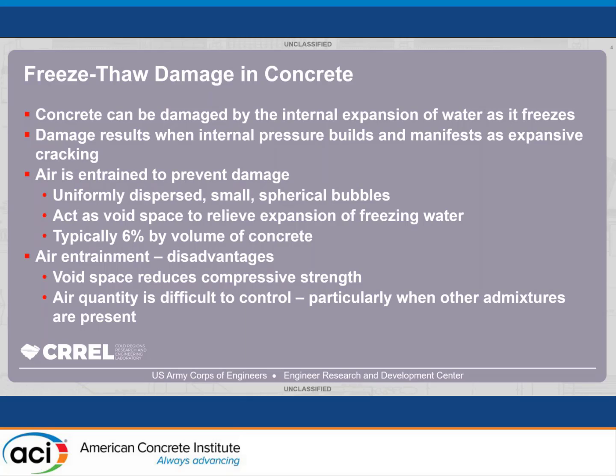As many of you know, I'm sure, concrete can be damaged by the internal expansion of water within the pores of concrete as it freezes. That frozen water takes up a lot more space than the liquid water, so it can cause damage by having that internal pressure, needing to expand, and then cracking. And so air entrainment has been used forever in concrete to prevent damage. The way typical air entrainment works is with uniformly dispersed small bubbles, and once they go into the concrete, they act as void space, so when water does come into the concrete, it has a place to go and to expand.